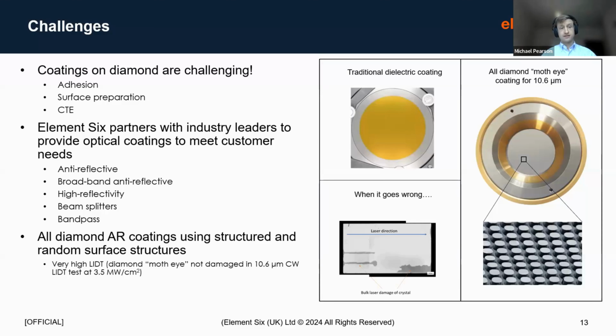The other thing that I'd just like to highlight is you can achieve good anti-reflective properties with an all diamond solution. So if you structure the surface of the diamond, so a moth eye type structure as is shown on the right hand side of the slide there, you can achieve pretty good transmission. So maybe up to sort of 97–98% transmission. That particular structure is for 10.6 microns, which is a product we've made historically.